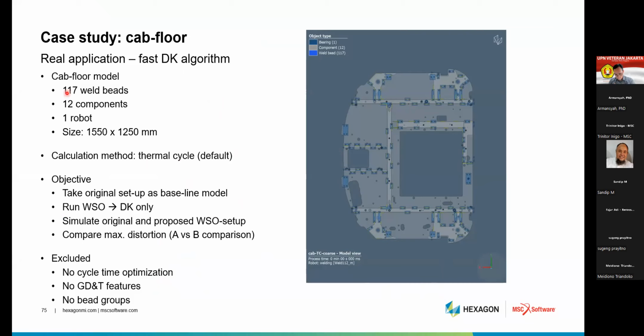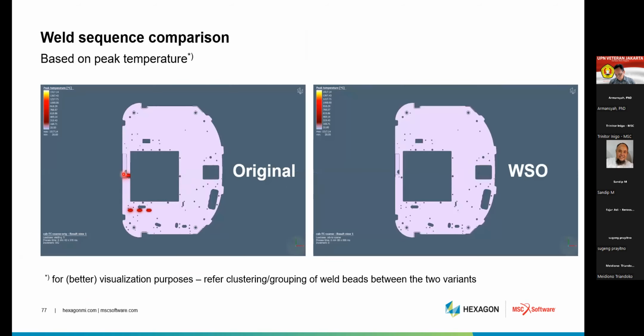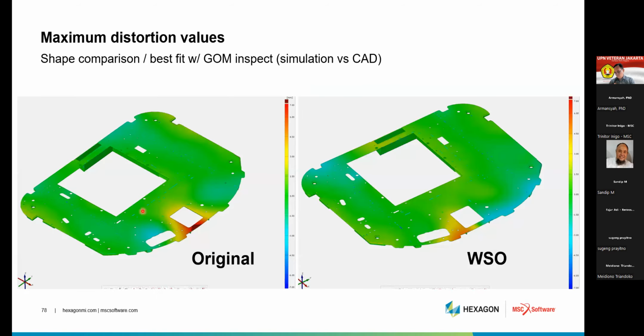This is the cab floor. There are some 117 weld beads and 12 components. This is a WSO model. This was the original weld sequence, and you can see the welding happening over here. Our software predicted the optimized weld sequence, and it takes only 10 to 15 minutes. Within 10 to 15 minutes, you will know what my welding sequence should be to have the minimum distortion or stresses. With the original, you can see there was high distortion, beyond 7 mm. With the welding sequence optimizer, we are getting the distortion below 4 mm.